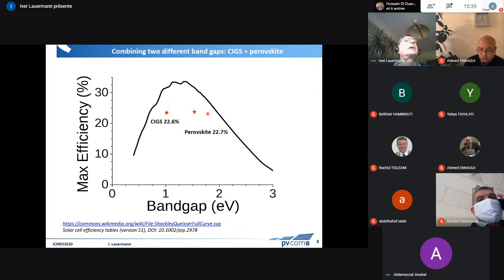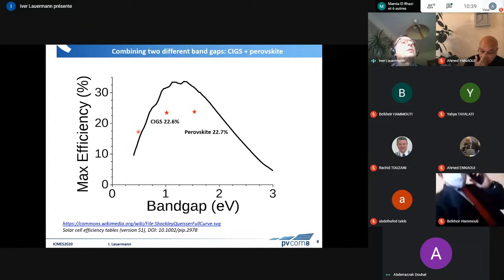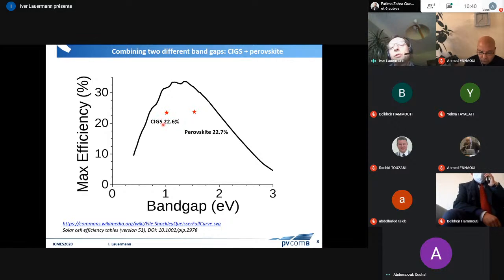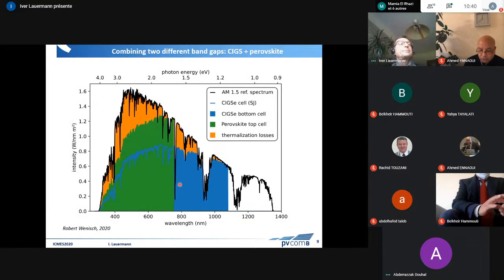Now, if we look at single materials today and we look at this efficiency curve, which is basically the Shockley-Queisser equation of the theoretical limit for single junction solar cells, and we look at the thin film material CIGS, I'll come to that in a moment. We are here in the range of 23%, today a little higher even, and this is for small laboratory samples. And if we look at this new material, which I'll also come to in a moment, perovskite, we are also in the same range. And these have different band gaps. And now we can combine these and look what we get.